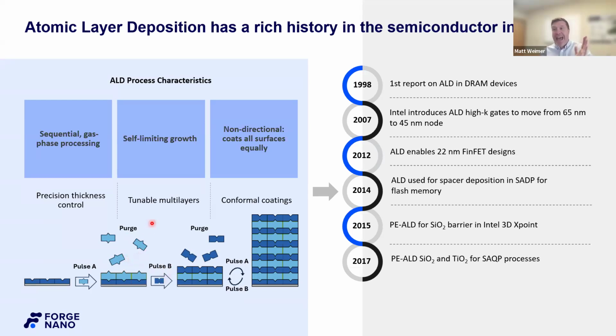So look, we've done one half cycle, not even a full cycle. Let's move into the complementary precursor. We call it the B precursor. It's these blue bow ties. Those dark blue divots meet up with those spikes, and we do the same thing. We get a nice monolayer of coverage. And of course, now we have to purge again. That slow step. We've now completed one cycle of ALD.